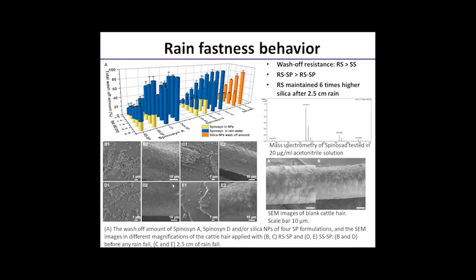The field emission SEM image can be used to directly observe the residue of nanospinosad before and after 2.5 centimeter artificial rainfall. After applying the spinosad formulation onto the raw cattle hide, numerous spherical nanoparticles can be observed attached on the hair cuticle, in both cases of the smooth and rough nanoparticles. After the 2.5 centimeter rainfall, a significant amount of the rough nanoparticles can still be observed attached on the cuticle of the cattle hair. In comparison, smooth spinosad shows much lower nanoparticle distribution on the hair cuticle, indicating most of them have been washed away by the rainfall. This huge difference between rough and smooth nanospinosad clearly demonstrates the function of the rough surface in inducing high adhesion towards the cattle hide, which contributes to high